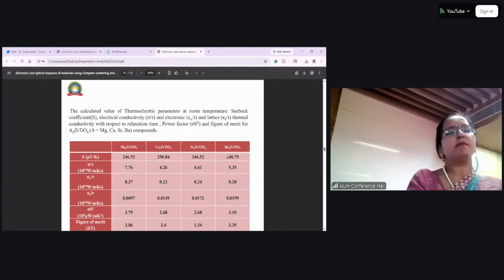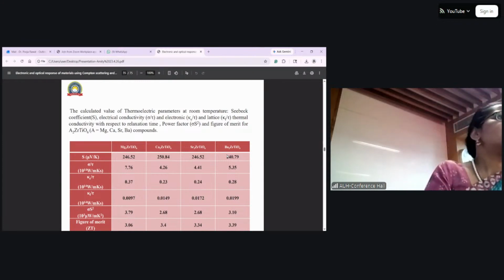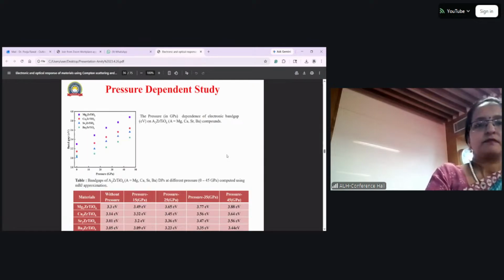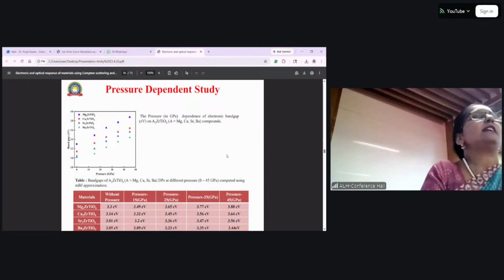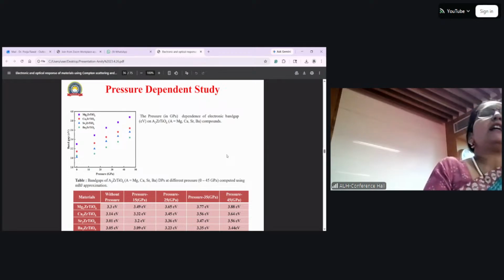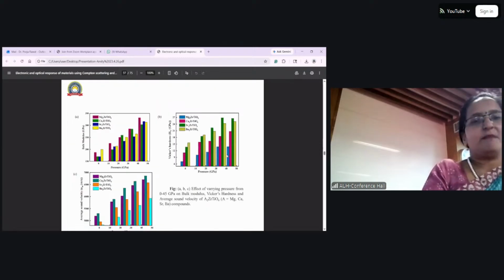Then this is the summary table for the thermoelectric parameters of all the compounds, and we found that these materials are suitable for thermoelectric application also. Then what we have done is we have applied pressure on these materials from 0 to 45 GPa. And if we apply pressure on the material, whether these materials change their properties or not, that we have also explored. We found that for all the materials the energy gap was increasing, and they all were stable. Even if we apply pressure, they all showed good absorption in the UV range. They all had mechanical stability based on the mechanical parameters that we calculated.